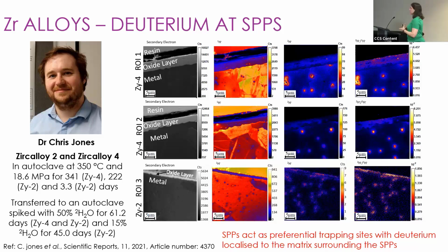But he started off by looking at these alloys to begin with, and we found something that we didn't expect, which was we found these regions in the metal. So again, here we've got resin, the oxide, and the underlying metal here. And we could see very clearly in every sample we looked at these deuterated hotspots, essentially.